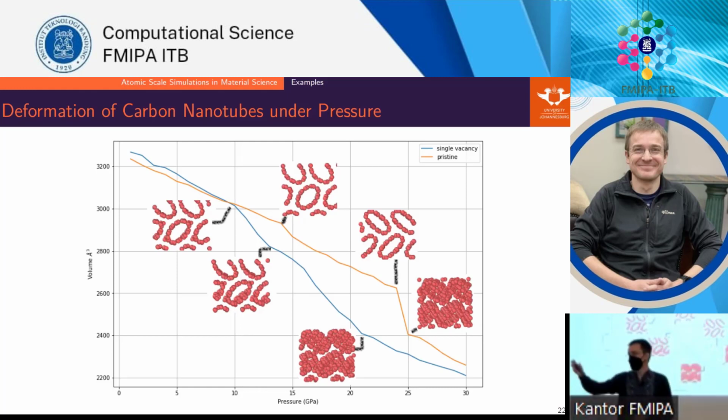And then where the first black arrow is, we see at 15 gigapascal, there's now all of a sudden a dip, right? At that point, the structure slightly collapses. It cracks a little bit, it moves. And then again, it now has this oval shape. Before, the nanotubes try to stay round. They just become closer together, the atoms, right? But at some point, that's not feasible anymore because they become too close. So they need to lower the symmetry.